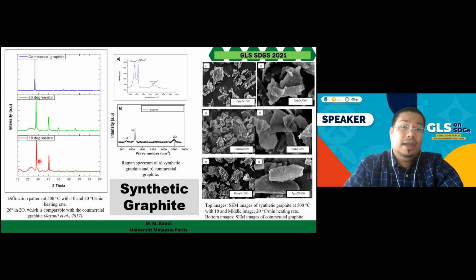So if you compare the synthetic graphite that we produce from oil palm trunk and the commercial graphite, it's almost identical in terms of the peak there. And then in terms of the Raman structure, in terms of the Raman spectrum, this is basically our synthetic graphite that we produce from oil palm trunk, and this is commercial graphite.